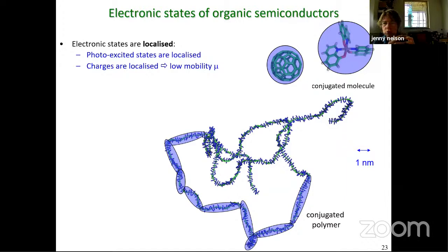And excitons are typically Frenkel excitons that will be localized in a small volume of space, partly by the dielectric properties, partly by the electron-phonon interactions in this soft molecule, and partly by the fact that the material is actually disordered. So excited states are localized, and moreover, charged states are also localized, and that gives rise to low mobility. And as well as the localization, we have the fact that because these are soft materials, they're not strongly